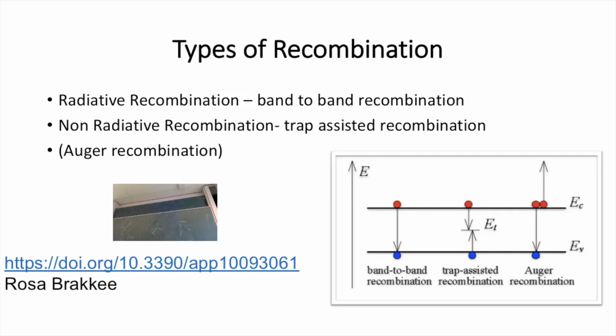For me, it's also counterintuitive because I'm used to fluorescence being a local property of a chromophore, and you want to quench the emission by electron transfer. That is what I did in my PhD. But if you look at a semiconductor, if you have a solar cell, but you're not making current with it, but you're just shining a light on it, and the electrons cannot go anywhere, they will be lost somehow. So if there are dark trap states, then the electrons will go through these states and get lost, get dissipated. But if they cannot do that, then they can only emit light.